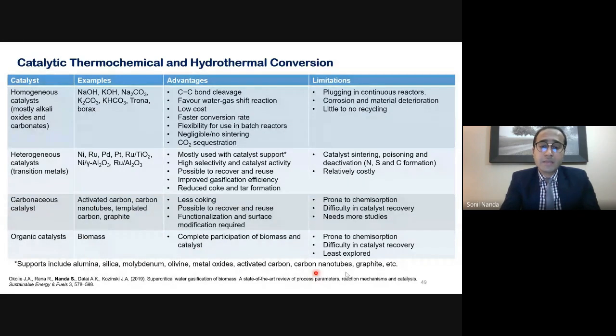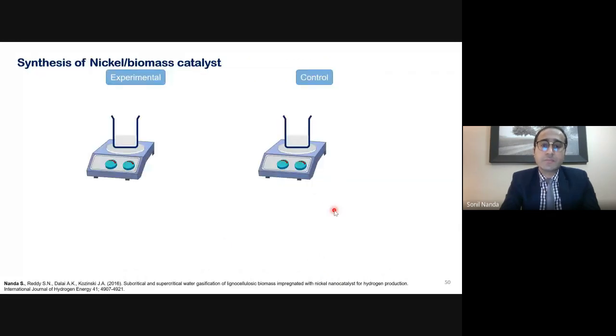These types of catalyst supports are very less explored, but we did successfully perform this experiment in one of our studies. Here we took nickel and tried to impregnate the nickel catalyst onto the biomass species. There are two different sets of experiments: one was the experimental and the other one was the control. What we did is we took water, added nickel nitrate hexahydrate into this water, and added biomass into that in the experimental. But in the control, there was no nickel nitrate solution. It was just water and biomass.